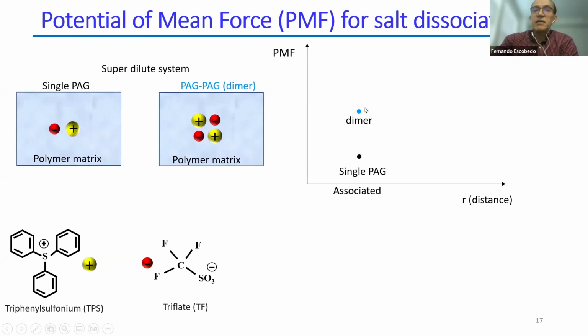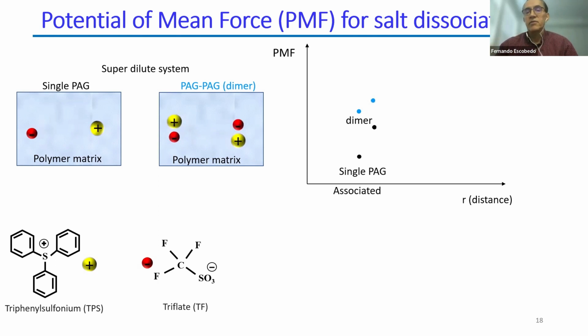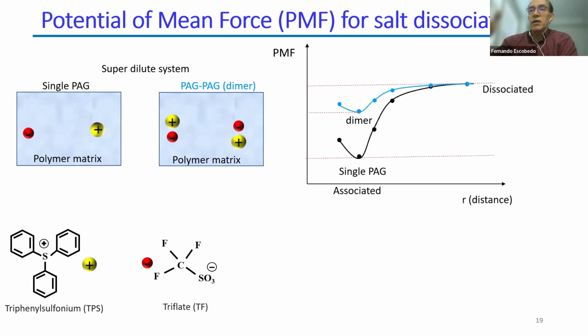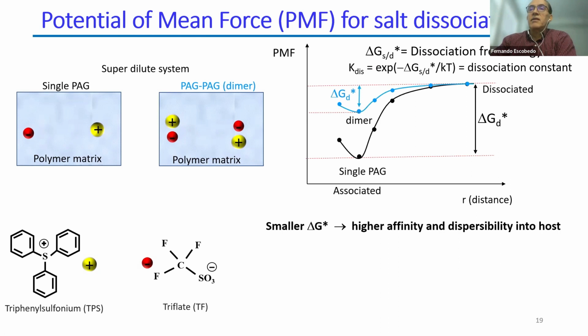So it will have some free energy, but if you now try to separate these moieties, for example in the case of a single PAG, you try to separate the two ions, then there will be a penalty that will manifest as an increase in the potential of mean force. A similar thing will happen if you are trying to pull two salt molecules apart. You can continue with this calculation so that at the end you end up with a full curve of this process, up to the point where they're fully dissociated at long distances. From here, you can extract these dissociation free energy barriers, these delta G stars, as I'm going to refer to them, with the key idea that the smaller the delta G star, the smaller the barrier, and you will have a higher affinity and dispersibility.